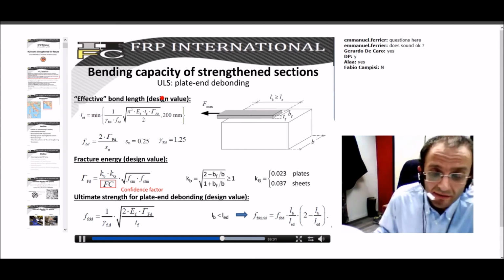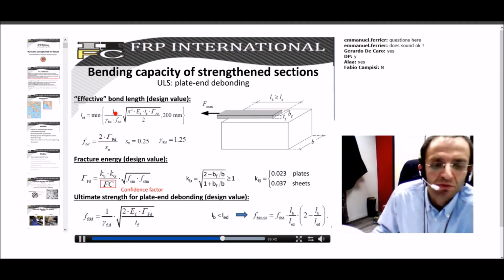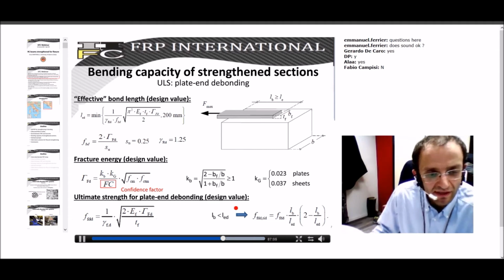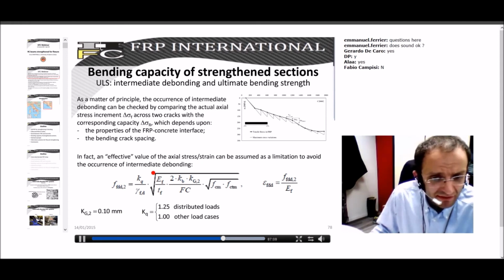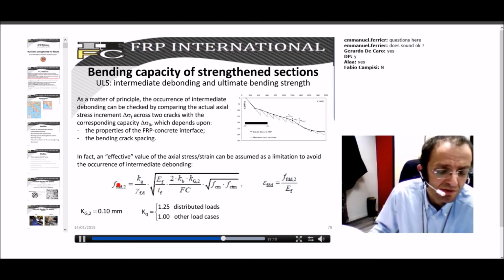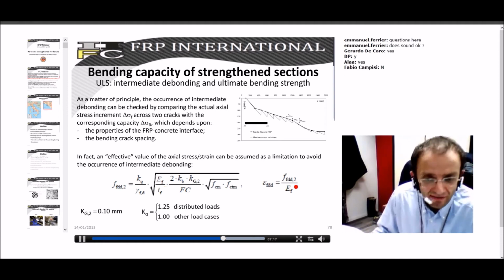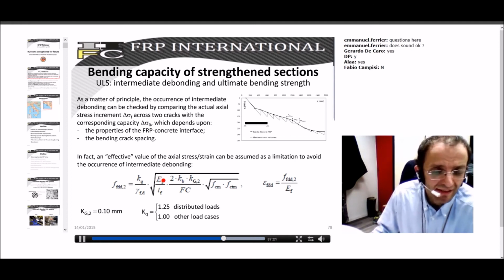These are some formulations provided by CNR. As you see, you can easily recognize here the formulation for the design value of the transfer length, which resembles the one I've shown you in my presentation. This is the formulation of fbd, which is also similar. Here, this is the design value of the maximum force which can be transferred in the bond in a pull-out test, which means the maximum force which can be transferred at the end anchorage in end debonding. And this is the formula provided for intermediate crack-induced debonding. So you can evaluate this force, this strength, or the corresponding strain here, just by considering the axial stiffness of the material and properties of the interface.